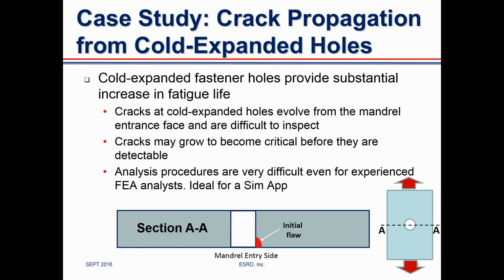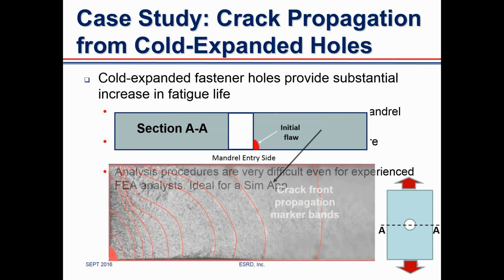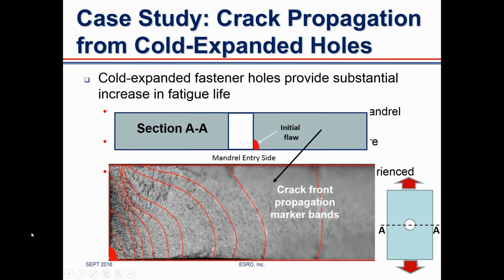Analysis processes are very complicated for this type of problem, even for experienced FEA analysts, which makes it ideal for a simulation app. Just to give you an example of the class of crack propagation that may occur, this is from an experiment that was performed in which marker bands were used in the spectrum in order to be able to trace the crack front from an initial flaw on the entrance side. So this is this portion here magnified, and what you see is that the crack front grows substantially on the inner side, the not visible side of the part, before it actually penetrates and is visible from the outside.